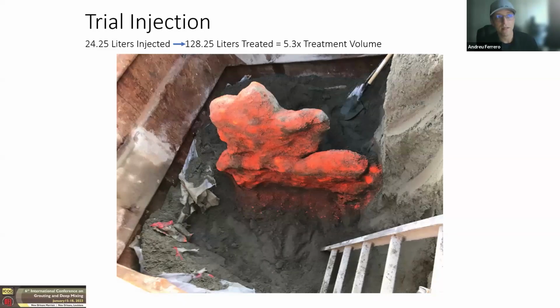So what that tells us is that the material in the soil is going to be much, much denser than the material in the cup test. And we see that here, this material has a consistency of weathered sandstone, fairly tough. You can hit it with a hammer a couple times before it'll fracture and break. And the sand doesn't ravel off as you're touching it. The dimensions of this guy are about 7 feet long across the base, about 5 feet tall, and on average about 11 to 14 inches in width.